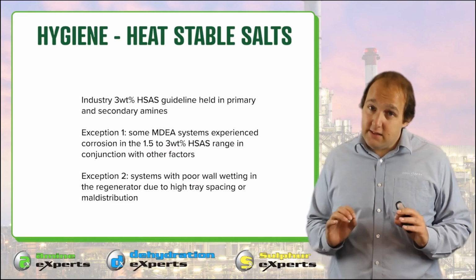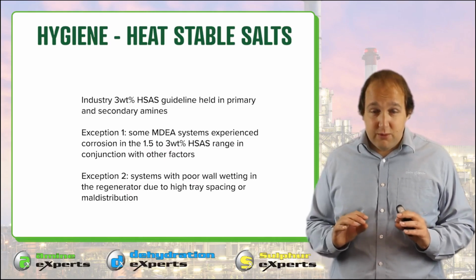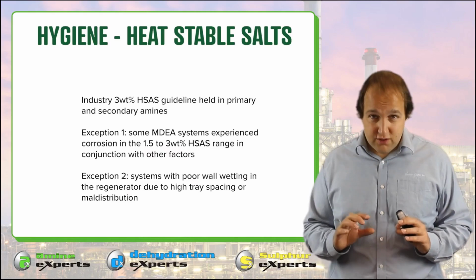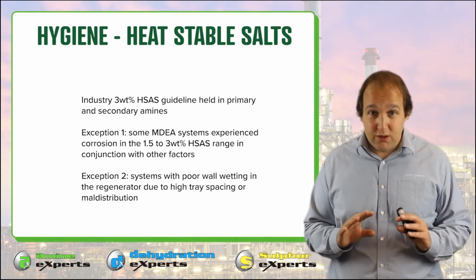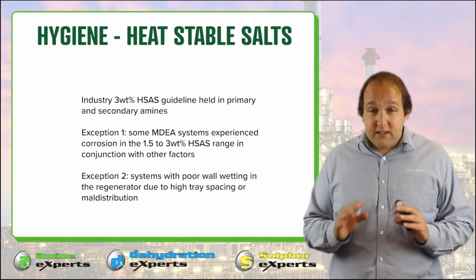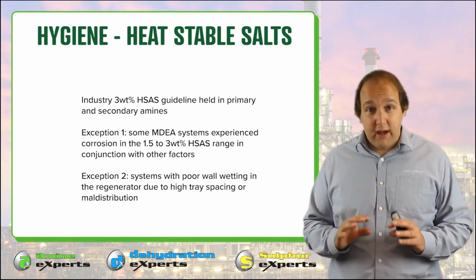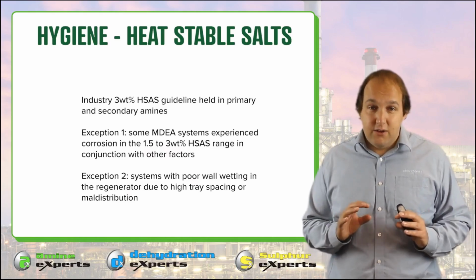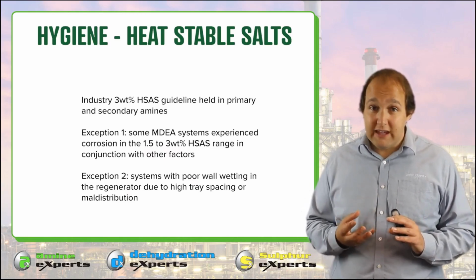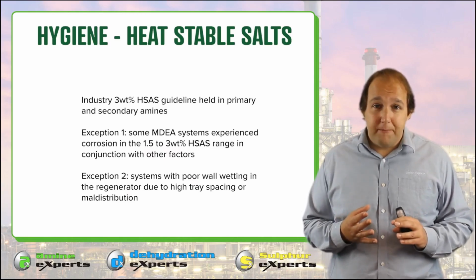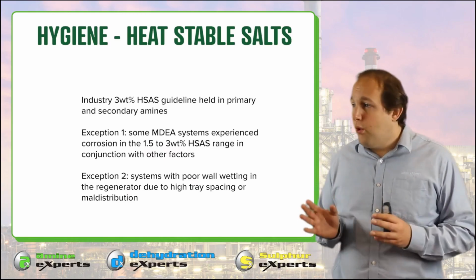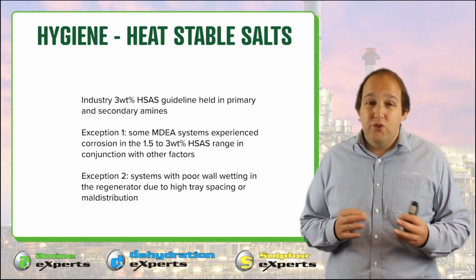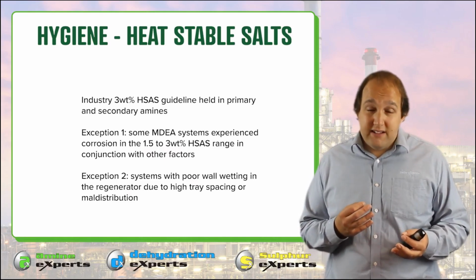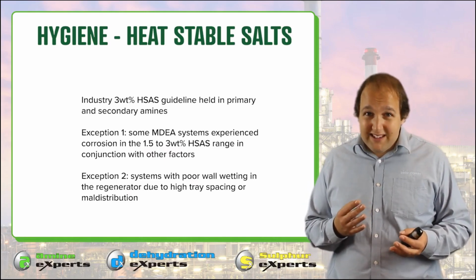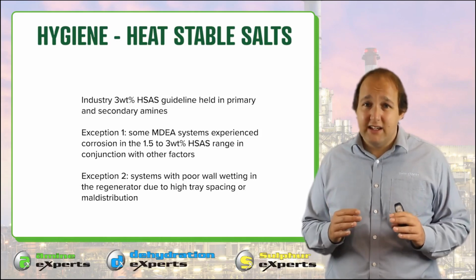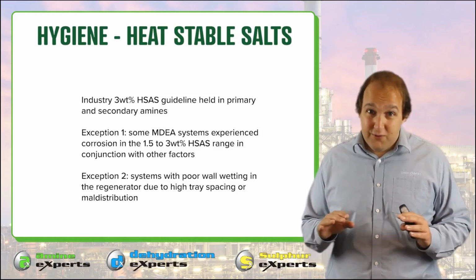Where we did see failures below 3%, there were two specific conditions. The two exceptions to the 3% rule are sweet systems, so systems with a lot of CO2, and MDEA. MDEA is actually the weakest of the amines, and when it's in a CO2 system, it is more vulnerable to attack by heat-stable salts. So with MDEA systems, generally, you may want a slightly lower limit for heat-stable salts.